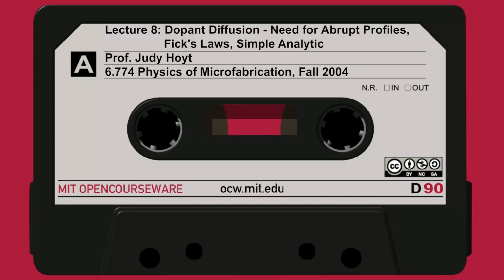As it turns out, we'll see that D is related to the atomic hop rate, or the jump frequency, over some kind of energy barrier. This energy barrier is associated with the formation and migration energies of mobile species. D is generally exponentially activated, so it depends on temperature in an exponential fashion.